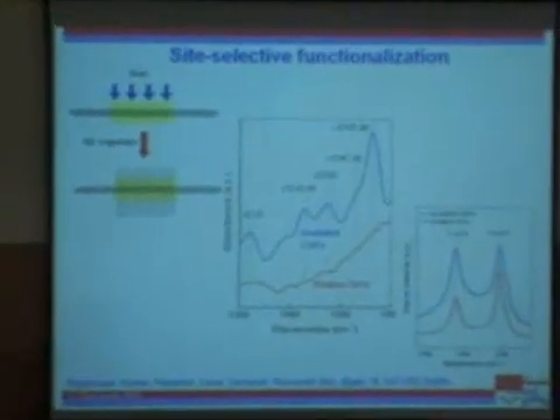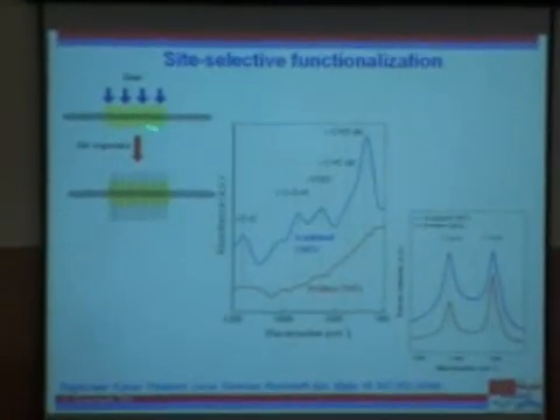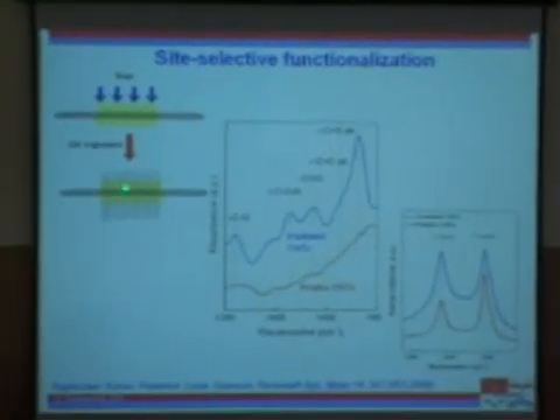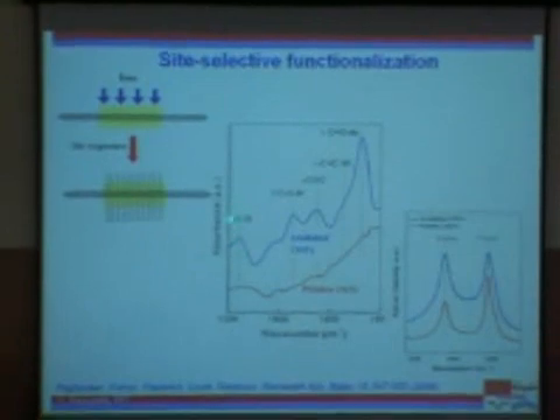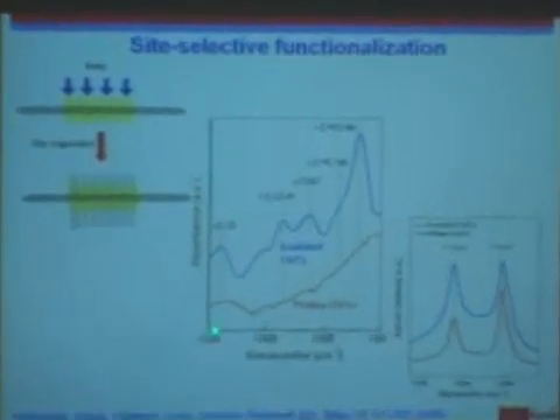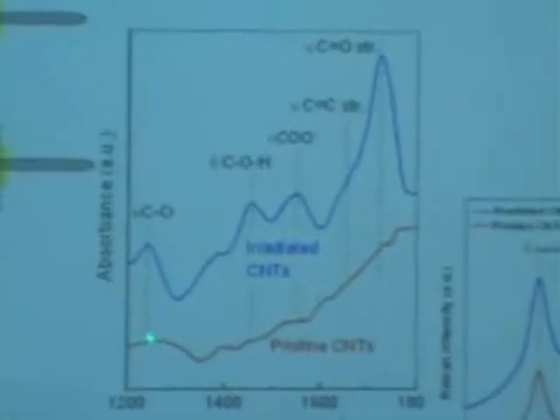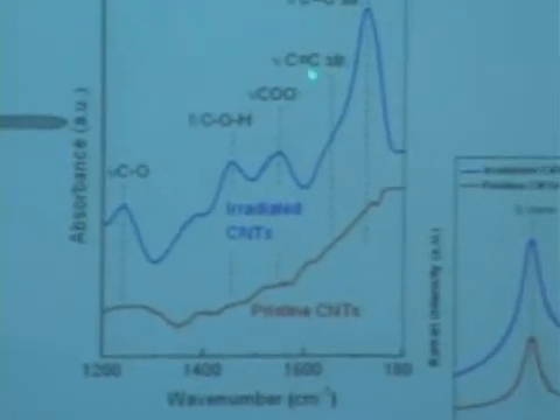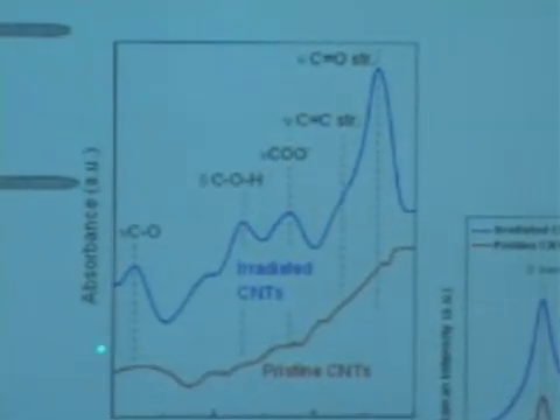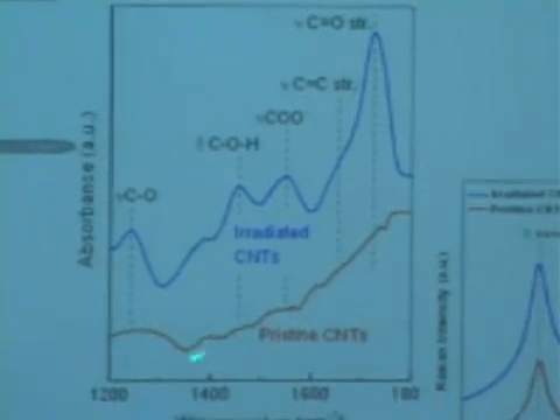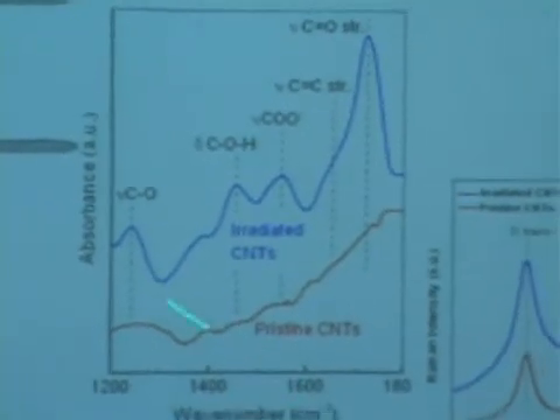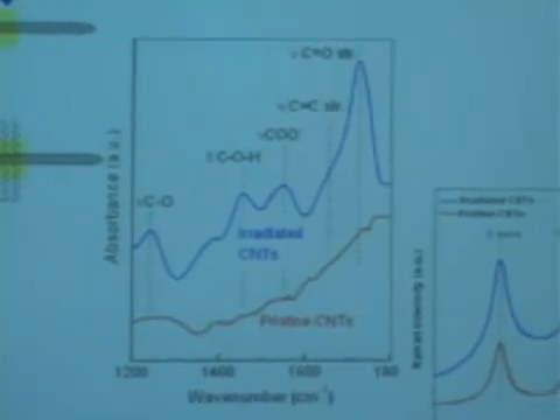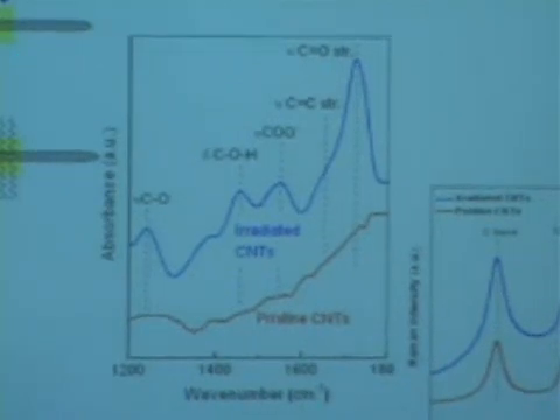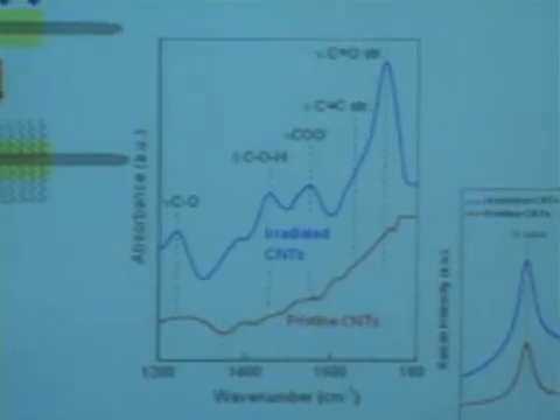Okay, so now I'm breaking bonds with ions, and then I'm exposing it to air. This is just one simple example. You can see this is actually the infrared spectrum. When I have irradiation, I can see all these carboxyl groups, allyl groups, and other moieties that show up, but when I have pristine nanotubes, nothing much happens. So what this says is, only in places where I hit them with ions, I'm able to functionalize. So I get site selectivity along the segments of the carbon nanotubes.